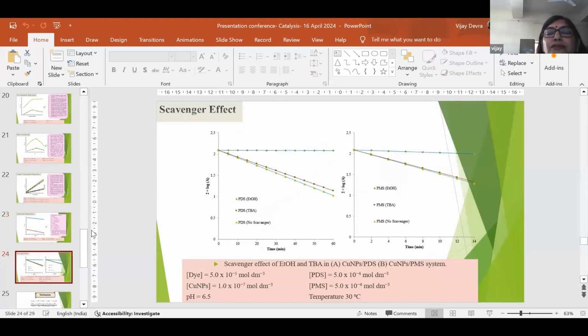And the scavenger effect is also studied. As we know, in the advanced oxidation process, sulfate and OH radicals are both active. So we determine the effect of sulfate radicals. We use ethyl alcohol and tertiary butyl alcohol to see the effect of scavenger. And as we see in both cases, in the presence of ethyl alcohol, the reaction is totally constant.